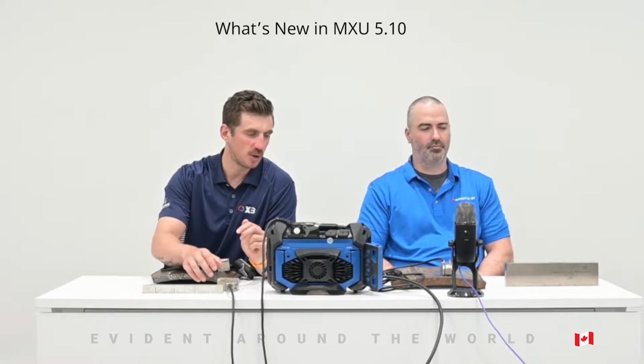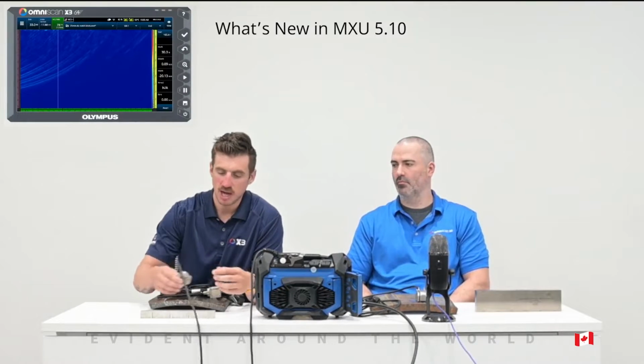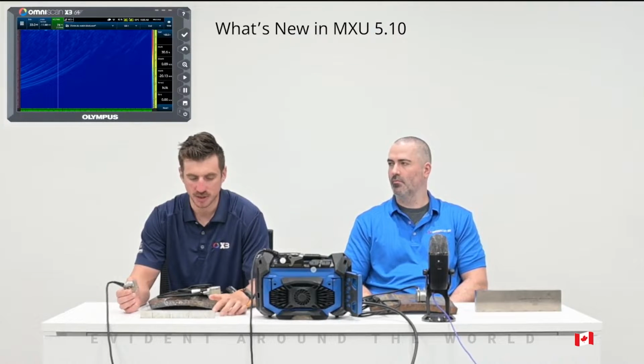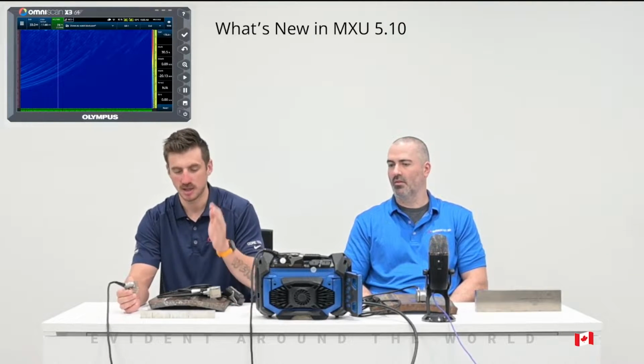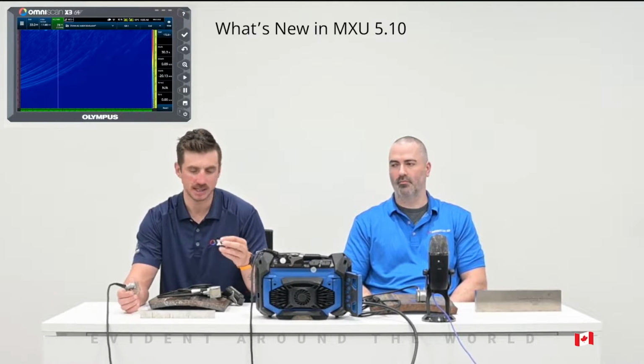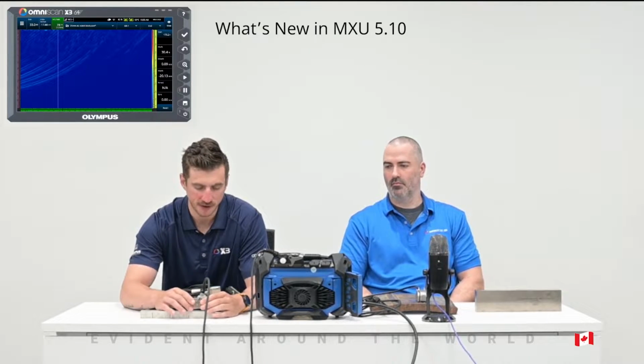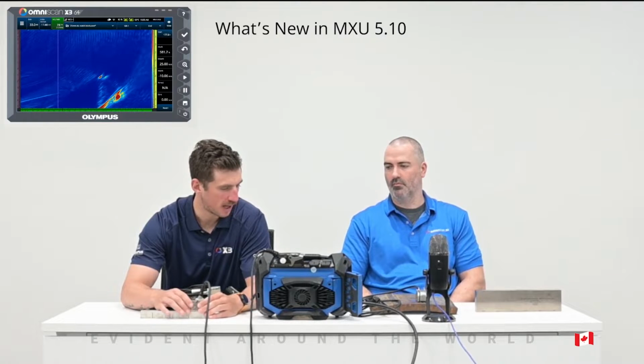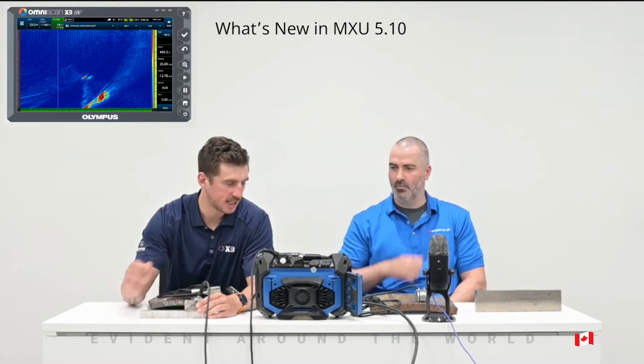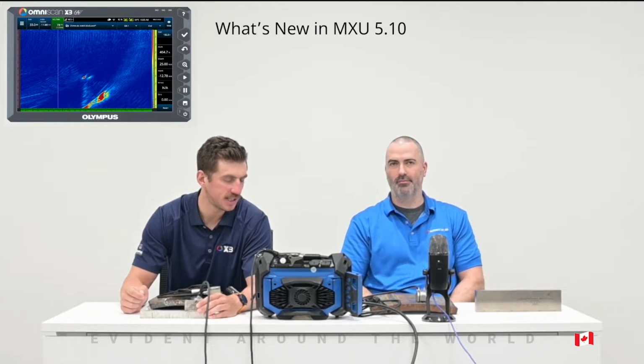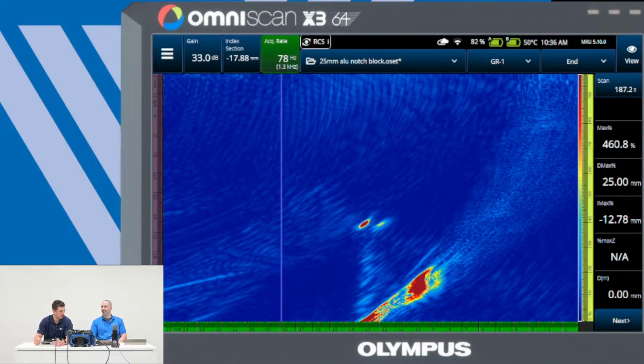So to show this, switching over to the X3 64, here I have a block with different height notches at 20, 40, 60, and 80% of my depth. Starting in conventional TFM, if I move over to my 40% notch, we can see the tip of my notch, but it's hard to see the vertical component, which is pretty characteristic of TFM. And my corner trap is going to be difficult to distinguish from, is it the actual corner trap or is it actually a defect that's going to be at that diagonal plane.